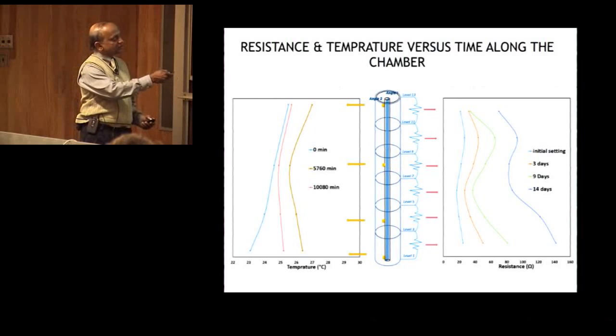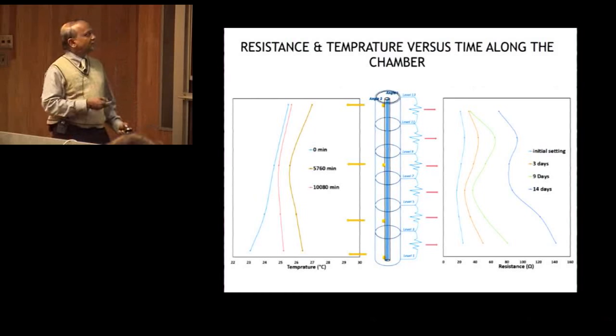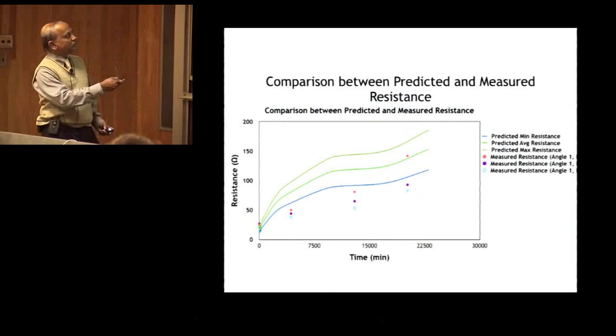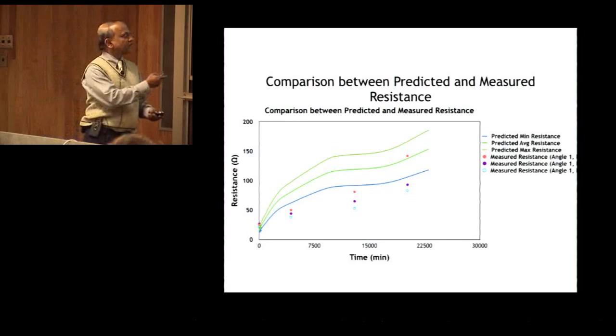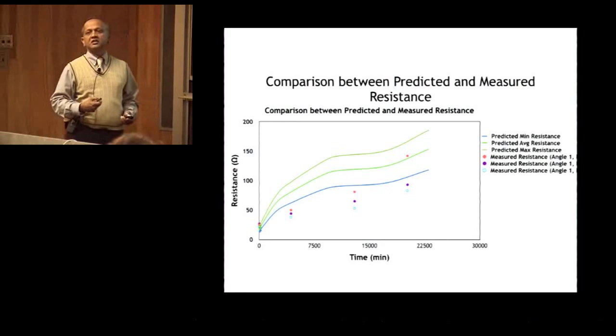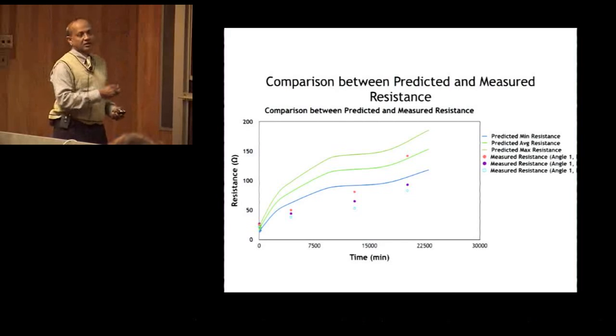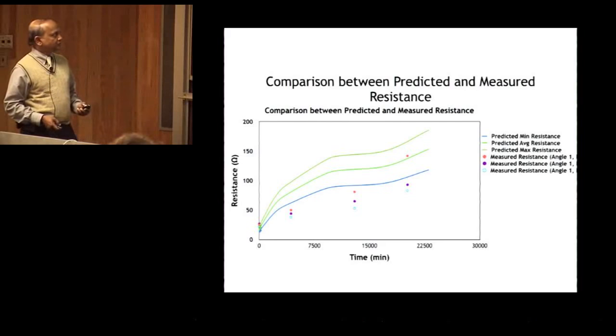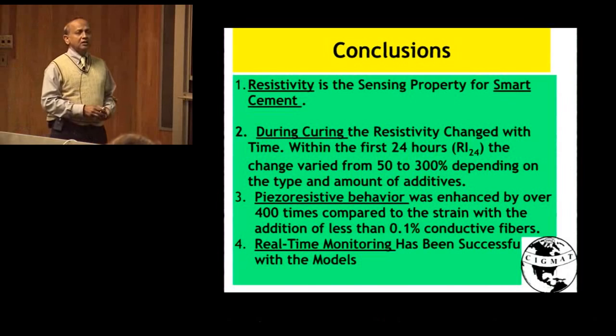And this all tells that cement is hydrating and we are fine. And then we also have the models to predict it, and you can see that cement resistance has increased, but it's a little less than what we predicted. So here you can see that we can reason it out with the temperature changes and things like that. This is just from direct resistivity measurement. So in a nutshell, this is what I want to conclude today.